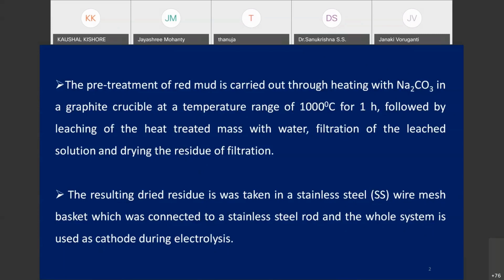So after water leaching, the resulting mass is dried properly and taken in the stainless steel wire mesh basket. We have prepared a basket-like structure from the stainless steel wire mesh, and here I am not preparing a compacted mass. As I have already told you, first you prepare the powder into a compacted mass. And in the slag case, it is not required to make a compacted mass because it is already in the solid or compacted form.